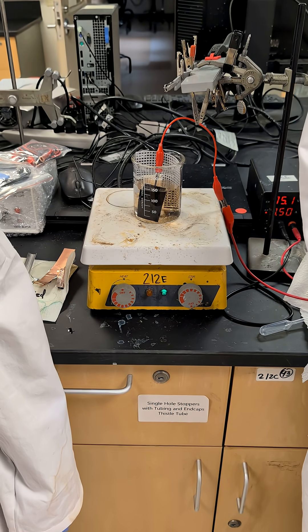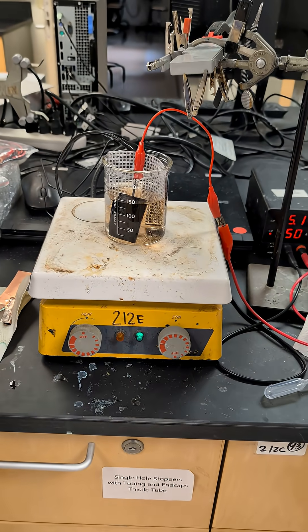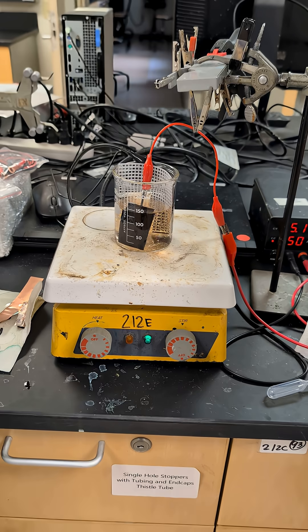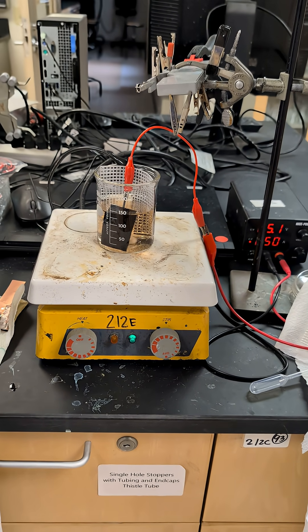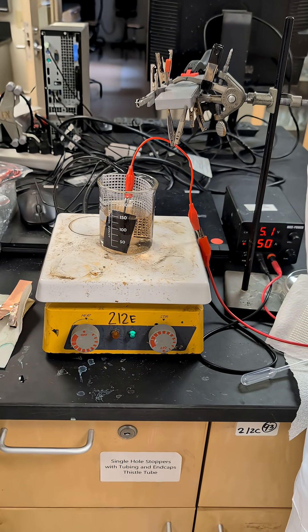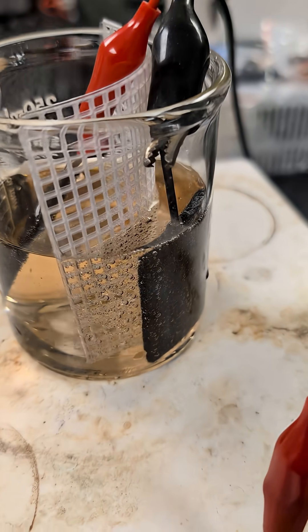Dave here from Western Pennsylvania, with two of my students. We're starting to study oxidation of graphite felt in 0.5 molar sulfuric acid with 0.1 molar manganese sulfate as a redox shuttle. The graphite felt is being oxidized for future use in supercapacitor design — where you see the red is the anode. The reverse electrode is the cathode, where hydrogen gas is evolving, which you should be able to see.